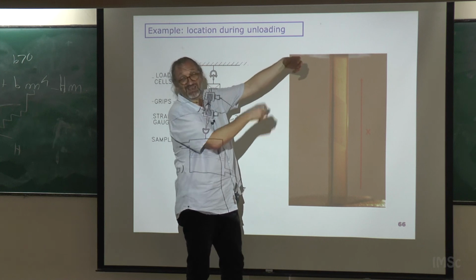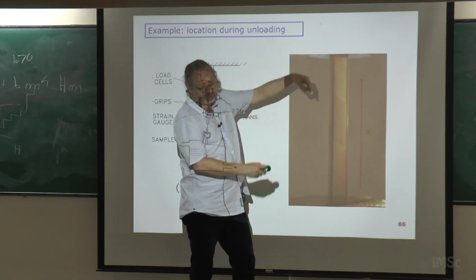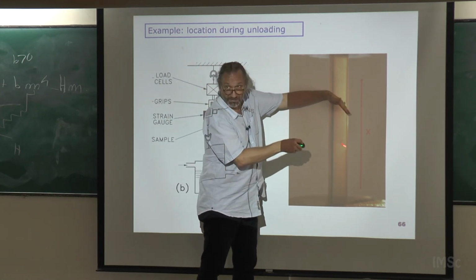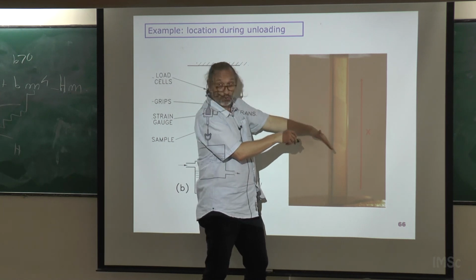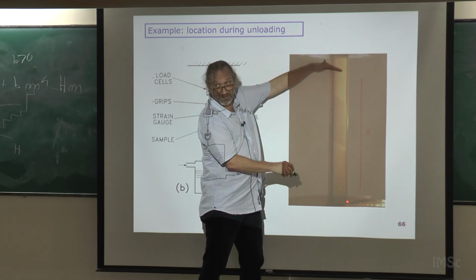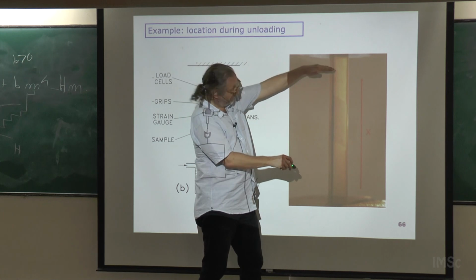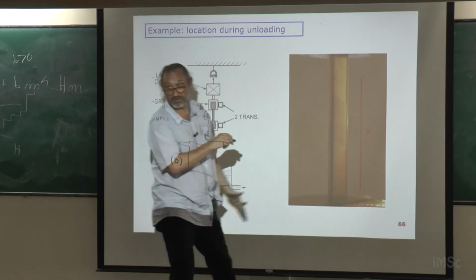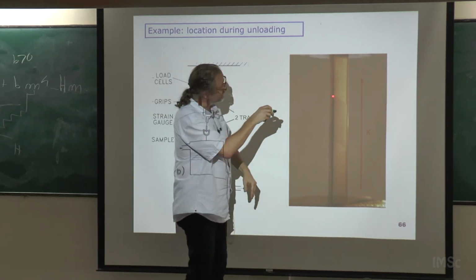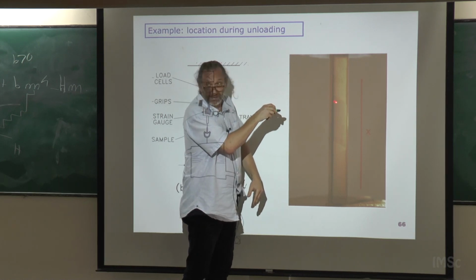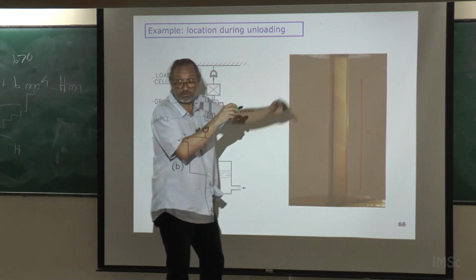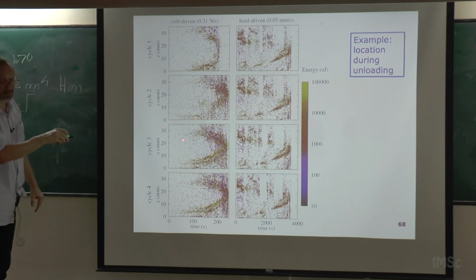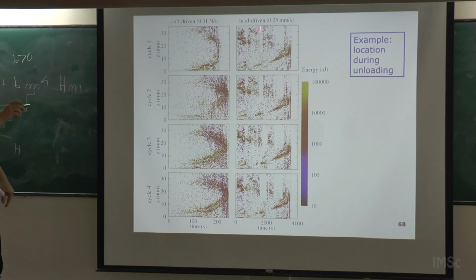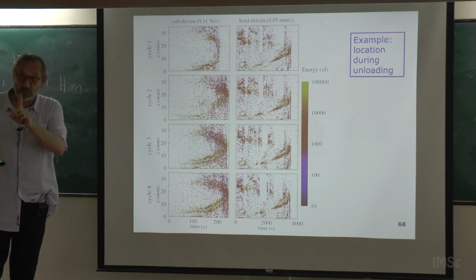Given this is a single crystal, given the orientation, it forms two domains here that when you load, they move like that. And then when you unload, that is what I was plotting, they move slowly towards the center. And the avalanches occur here, exactly here in the interface. And it's what you are seeing in this plot. And this is first cycle, second cycle, third cycle, etc. And this is hard-driven and soft-driven, and it's not exactly the same. Even the distribution of energies is different.